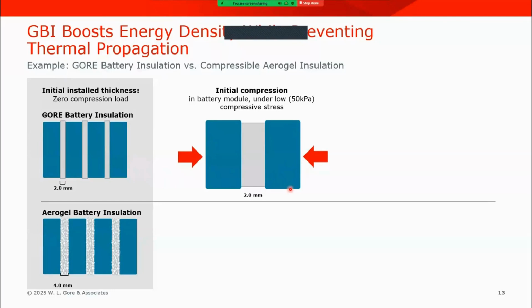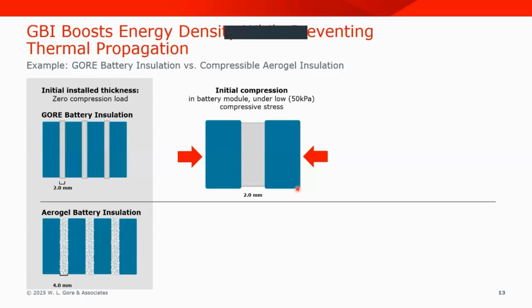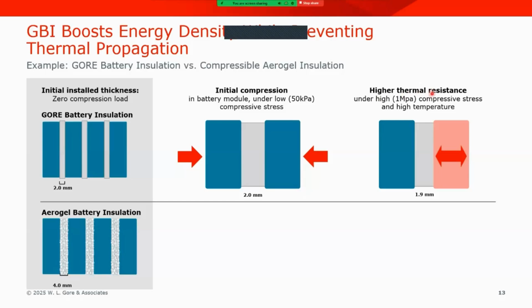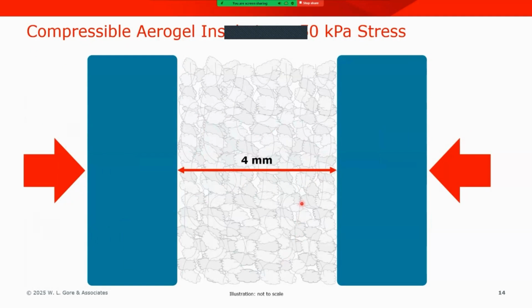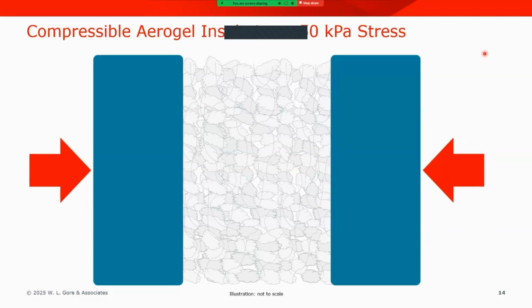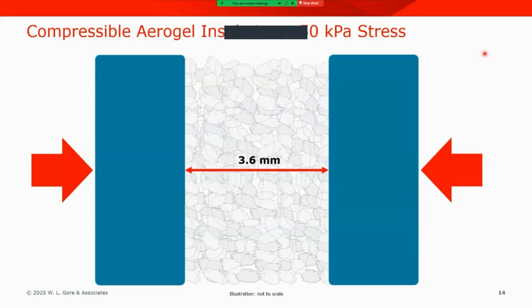But now imagine that this battery cell on the right were to go into thermal runaway. And when thermal runaway occurs, gases are produced inside the cell, which cause the cell to rapidly swell and to apply a much higher compressive stress on the barrier material. So imagine now under 1 megapascal of compressive stress, when the battery cell's in thermal runaway, GORE battery insulation is expected to maintain to within about 100 microns of that initial 2 millimeter thickness, and that is simply due to the low compressibility. Now let's compare that to what we might expect under the same conditions with an aerogel-based battery insulation. So again, imagine that we're starting with 4 millimeters, and we're going to apply just a modest 50 kilopascals of stress. Under that 50 kilopascals of stress, based on the stress strain curve, you might expect about 10% compression. So your initial 4 millimeter layer is now down to 3.6 millimeters.